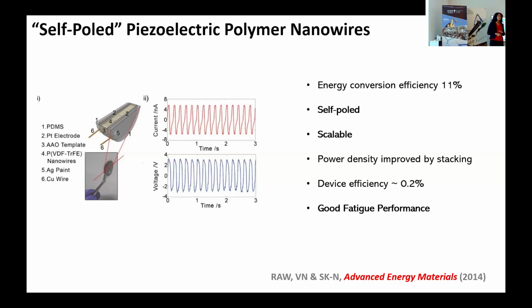But what we found is we didn't need to pole. So in this device, these were as-fabricated nanowires, and they were ready to go. So there was something in this growth process, and we kind of understand a little bit of how that is happening, where essentially as the polymer is infiltrating these pores, they're getting stretched along the direction of the axis of the pore. And this is actually another way by which polymers are poled.